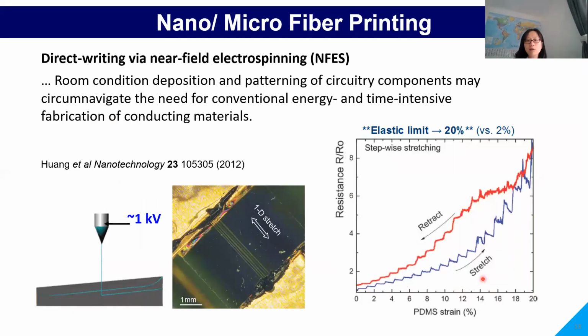In 2012, when I was a research fellow, a collaboration with the Nanoscience Center resulted in this very interesting work of direct writing composite microfiber electrodes. I was especially intrigued by the fiber direct writing method because it's room temperature direct deposition, which avoids the use of energy and time intensive fabrication. However, one of the major drawbacks back then is that we still need to use a high voltage, about 1 kilovolt, to initiate the jet.